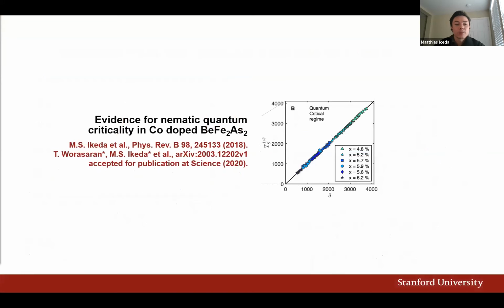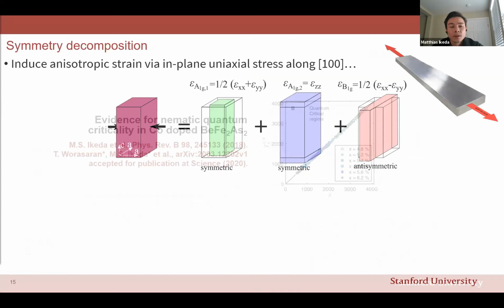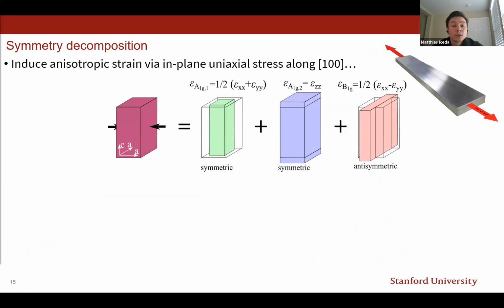And with this, I would like to come to the main part of this presentation, and that's going to be evidence for nematic quantum criticality in cobalt-doped barium iron arsenide. The experiments we'll be studying here are uniaxial stress experiments, once again, and we apply uniaxial stress along the tetragonal [100] axis, resulting in symmetry-conserving strain components and also symmetry-breaking strain components. Now, the symmetry-conserving strain components couple to all orders to the biquadratic nematic order parameter, and therefore can tune the phase transition temperature to any order.